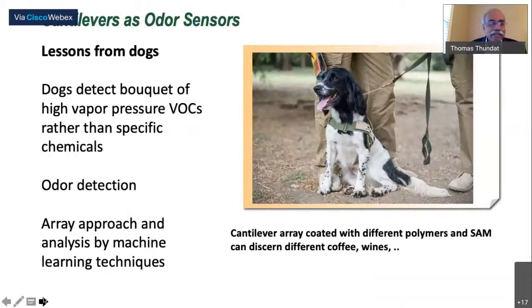So then we realized that these dogs may not be detecting, for example, explosives. They don't detect explosives because most explosives have very low vapor pressure. So dogs are basically detecting a bouquet of volatile organic compounds with high vapor pressure. So for example, TNT has toluene, acetone, limonene, and breakdown product like DNT. So the dogs basically look at the profile of these responses because they have lots of cilia in their nose.